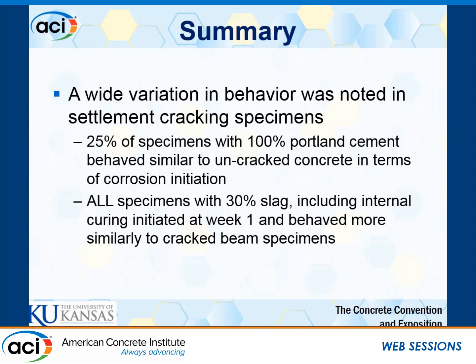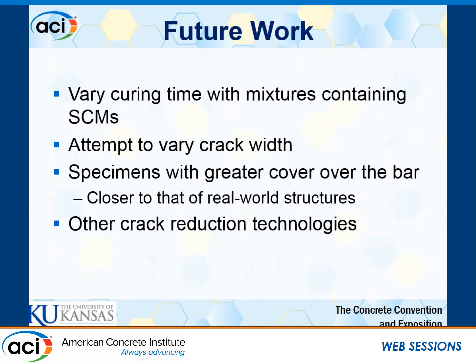And again, all of our specimens with slag or slag and internal curing initiated at week 1. And as was stated in the previous one, we believe that's for a similar reason. Those mixes with SCMs, without adequate curing time, tend to not have a very robust pore structure and have higher permeability. So the issue we're trying to address is increasing the curing time. Whether you're doing a corrosion test or something along the lines of durability, or even just curing a bridge deck in the field, a lot of documents and agencies are suggesting higher curing times for SCMs. So these specimens have since been cast and have just started testing.